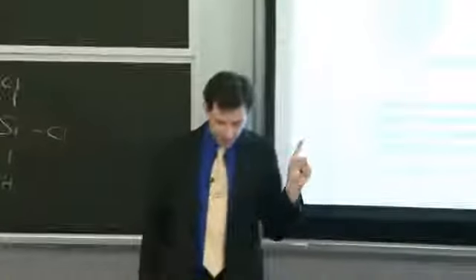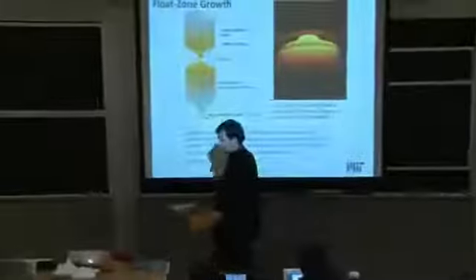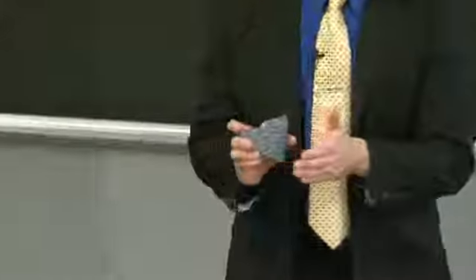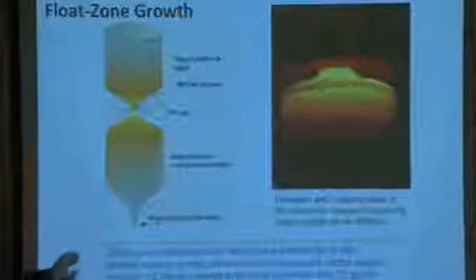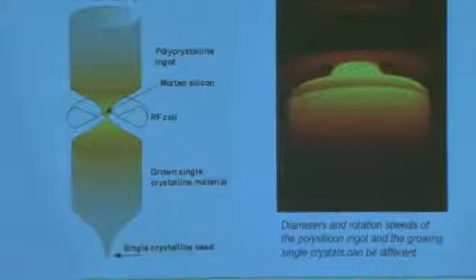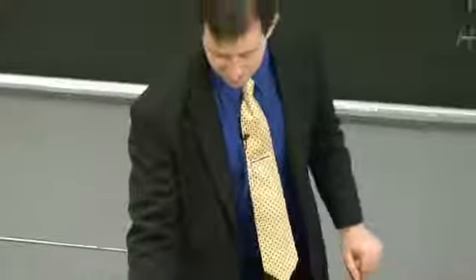So one variant of the single crystalline growth method is called float zone growth, where you take a rod of poly, much like that rod right over there, and you pass an RF coil, radio frequency coil, next to the rod. And what that does is essentially heats up the silicon. If it's doped highly enough, it will melt the silicon locally. Folks have probably heard of fancy high-end stoves that we can only hope to afford in 10 or 15 years. These stoves are inductive heaters, right? They're not resistive heating elements, they're inductive heating elements. And the way that works is you have a radio frequency source that is absorbed by, in the case of the RF heater, I believe it's a specific type of iron that the inductive heating ovens need. And so this RF coil here is emitting energy, which is absorbed by the silicon and melting it.